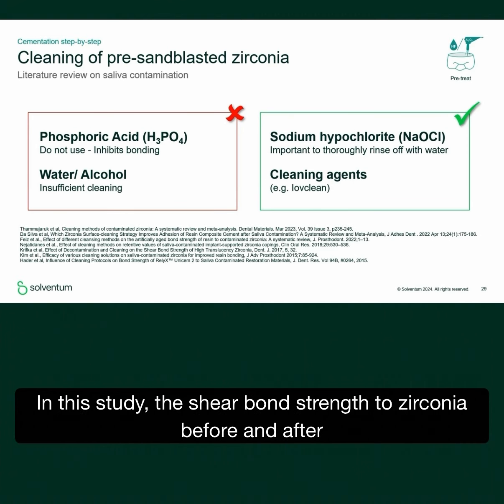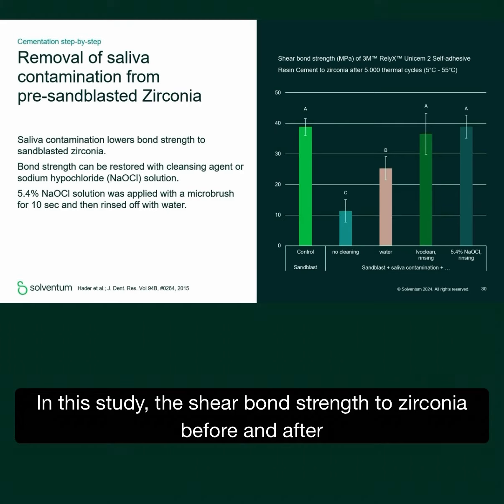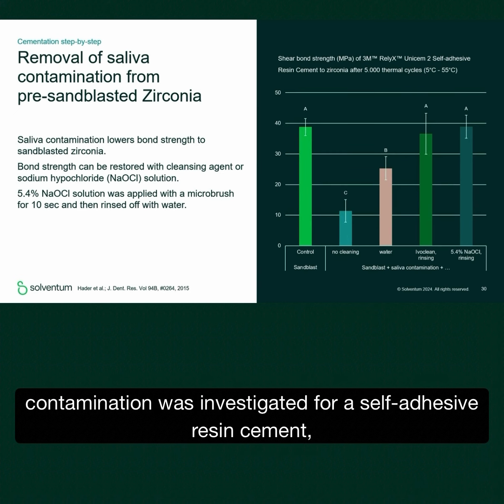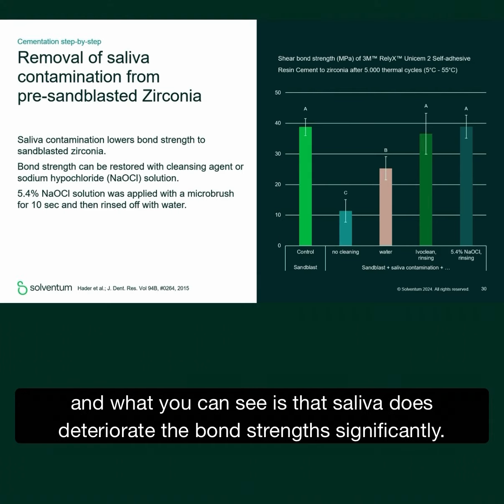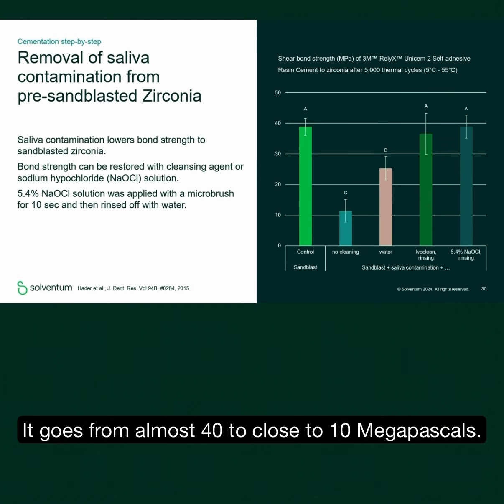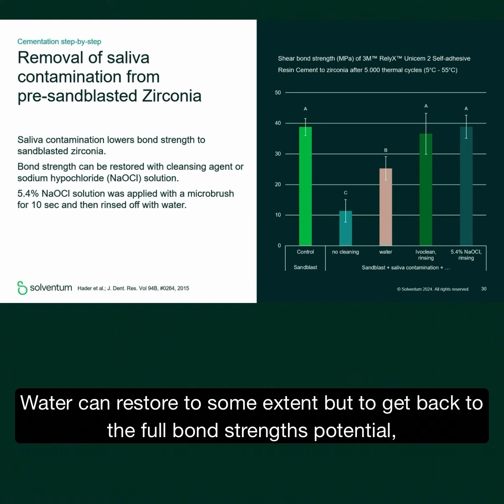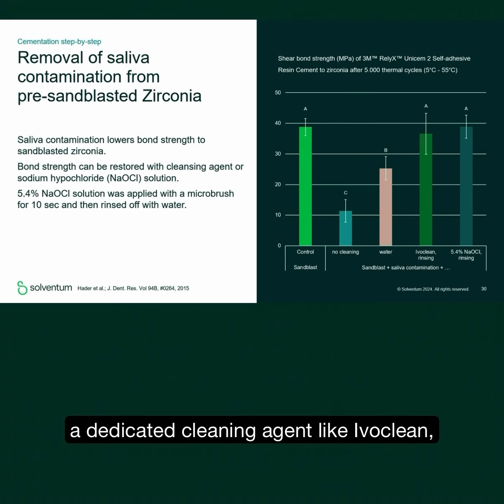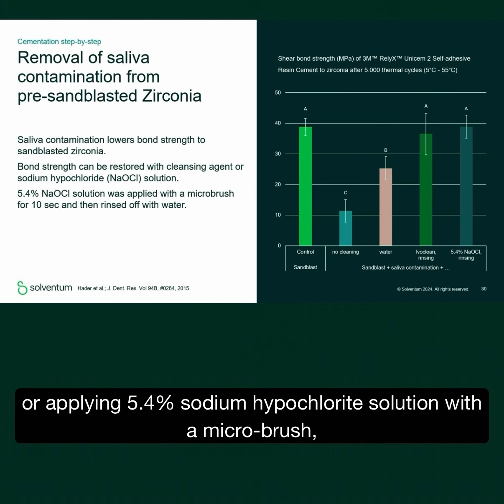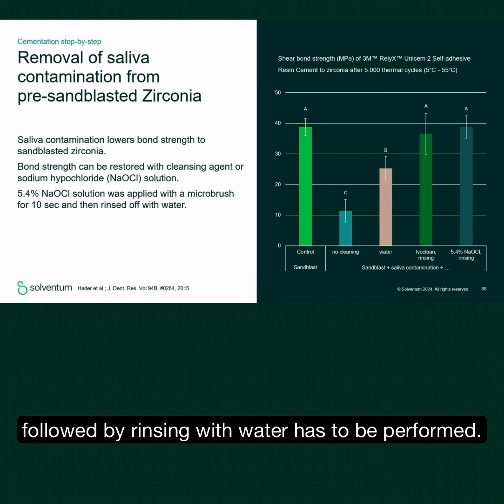In this study, the shear bond strength to zirconia before and after contamination was investigated for a self-adhesive resin cement. And what you can see is that saliva does deteriorate the bond strength significantly. It goes from almost 40 to close to 10 megapascals. Water can restore to some extent, but to get back to the full bond strength potential, a dedicated cleaning agent like Ivoclean or applying 5.4% sodium hypochlorite solution with a microbrush followed by rinsing with water has to be performed.